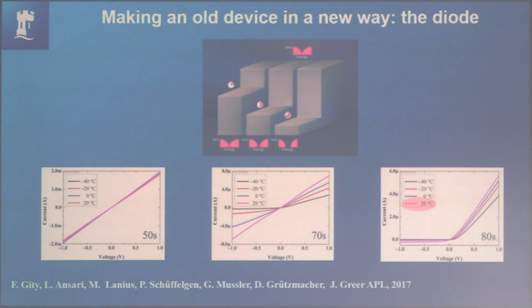Okay, so the first thing we tried to do was make a diode. And the idea is relatively simple. You take the thin film, you mask one side of it, and you etch for different times, and you get different thicknesses on the other side. You put some contacts on it, and you measure the current. If you just etch it for a short time, it just stays resistive. You etch it for a little bit longer, and you look at the temperature dependence, you can see that at low temperatures, you're starting to get an asymmetry.